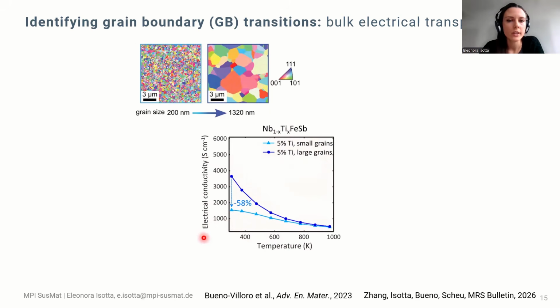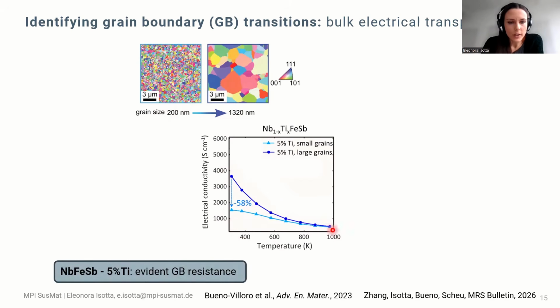Why so? Because they noticed that upon an increase in grain size, the sample went from having a low electrical conductivity at lower temperature to having a higher electrical conductivity at the same low temperature, with the behavior, as I told you earlier, that got increasingly suppressed as the temperature went higher. So in this case, with 5% titanium, we see a behavior that shows evident presence of grain boundary resistance.